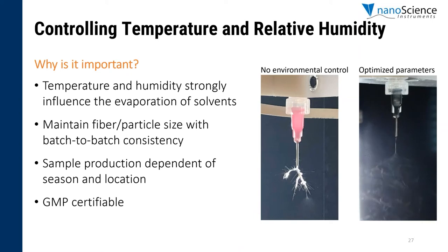Another thing is that in order to avoid non-reliable results, controlling temperature and relative humidity are crucial. But why is this important? As I mentioned before, temperature and relative humidity have a strong influence on how the solvent evaporates during the electrospinning or electrospraying process. As mentioned before, these two parameters are strongly influenced according to the location and the season of the year. If your building facilities are not too well controlled, you can easily see dry conditions during winter, high humidity after it has rained, or even fluctuations during a single day. Due to this, batch-to-batch reproducibility results may not be achieved.